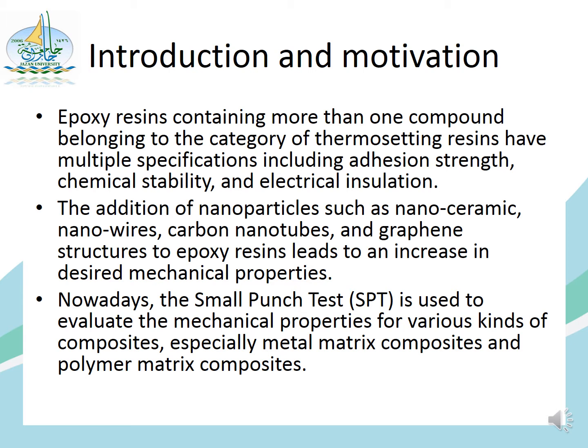Also, because of the crack pinning and plastic void growth, which arise from reinforcing the epoxy with nanoceramic, adding nanoparticles contributes to the increase of the composite toughness. Also, some researchers have noted that a nanoparticle size has a higher ratio of surface area to volume than that of large-sized particles, which makes the nano size distinguish the physical network structure.